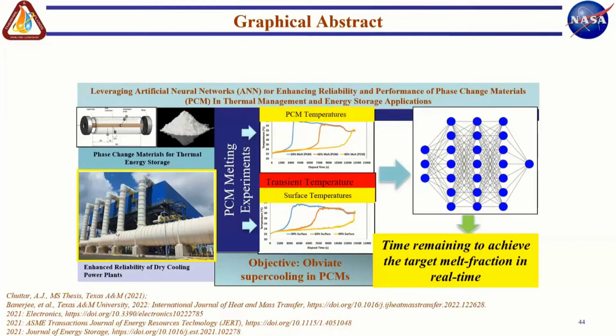And we wanted to do this prediction in real time. Let's say in a power plant scenario where you are looking at the time temperature trace of temperature within a molten salt vat, or of a phase change material vat, and you want to predict how much time you have before you hit 80% or 90% melt, because that's the point at which you want to stop. Because once you hit 100% melt, then it becomes an uphill battle to solidify that whole thing back. So just by looking at the time temperature trace, both within the PCM as well as on the surface of the container, we were able to predict when a particular melt fraction would be achieved in a heat exchanger filled with phase change materials. That's basically the overview of this work.